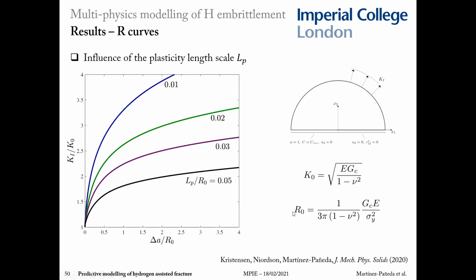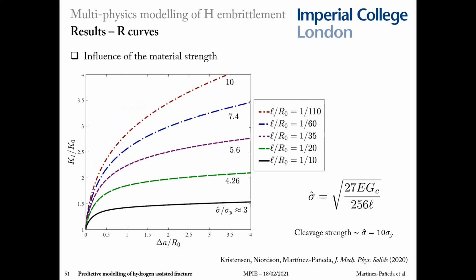And as a consequence, the ratio of the plastic length scale, which is a fixed material property that you can fit to a microscale experiment, and is roughly on the order of 5 microns, that ratio is going to increase because this is a constant property, and the fracture process zone, the region over which you have the gradients, is going to be smaller. And this is something that is also expected. We know that gradient effects are smaller in ductile fracture processes, where the critical distance is farther away from the crack tip, and the fracture process zone is large.